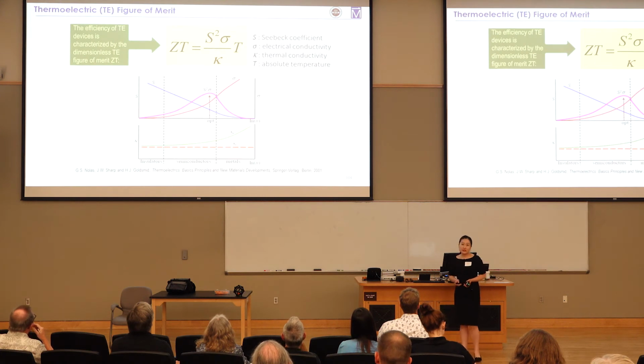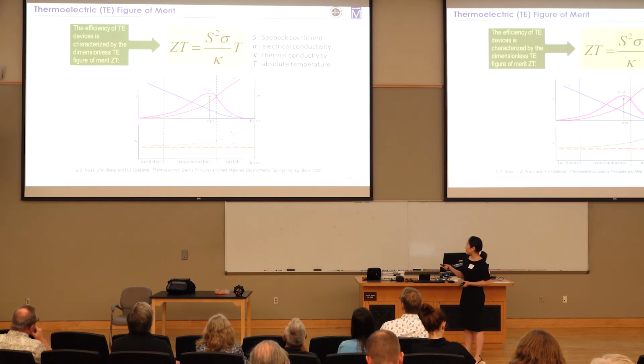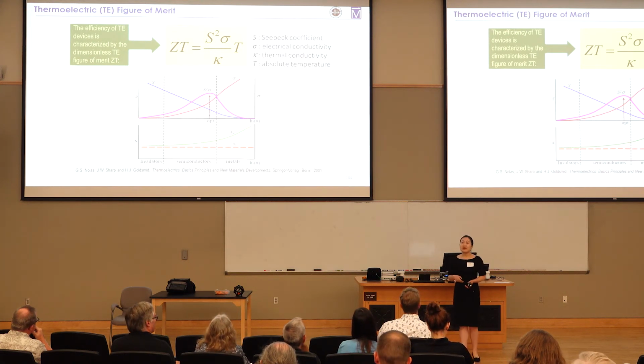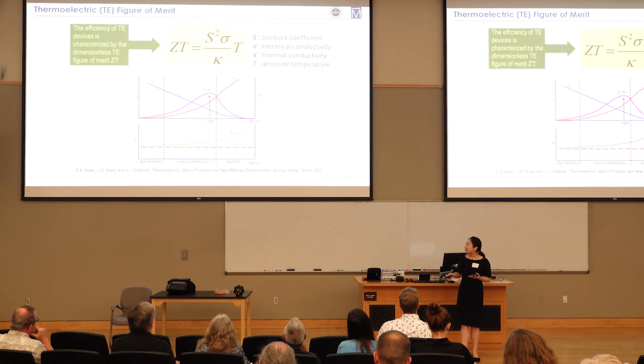Now, the efficiency of thermoelectric devices is closely related to this equation, which is the dimensionless thermoelectric figure of merit, ZT. It is composed of the Seebeck coefficient, the electrical conductivity, and the thermal conductivity. The focus of my research is to investigate materials that have the potential to balance these parameters very well and give us the best ZT value.